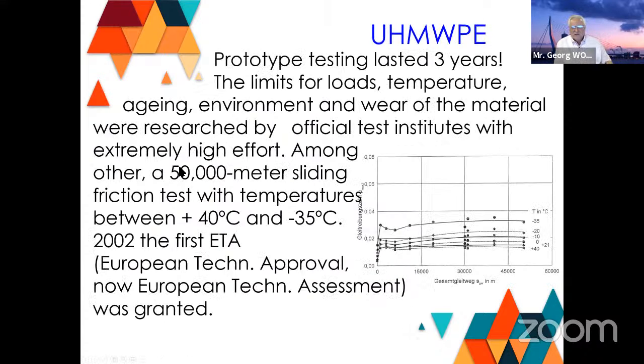The prototype testing lasted 3 years. The limits for the loads and the temperature, aging, environment, and wear of the material were researched by these official test institutes with very high effort. And you see here a picture of the 50,000 meter sliding. Here it's +40, -35. And that was then the basis for granting the approvals.